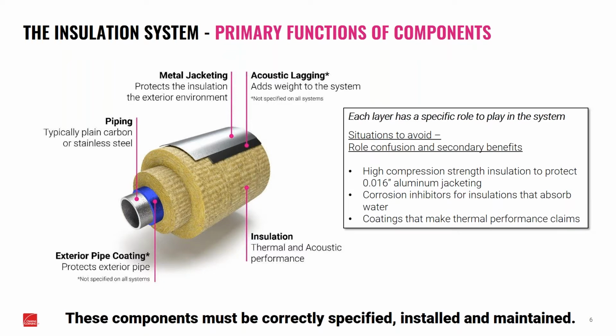Now, the other thing is using corrosion inhibitors for insulations that absorb water. Really, you want to keep the water out of the insulation to begin with. Although if you do have an insulation that does absorb water, it is a good idea to have a corrosion inhibitor, but it's not a catch-all. You really want to keep the water out of the system to begin with, so that corrosion inhibitor doesn't need to be used.